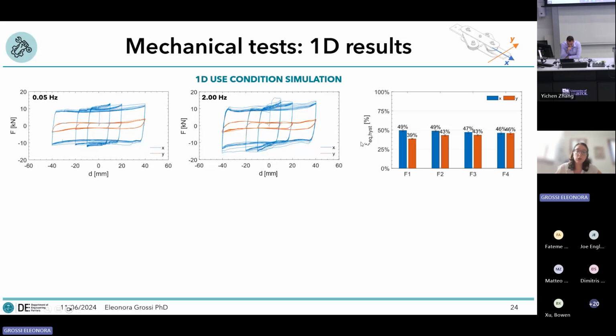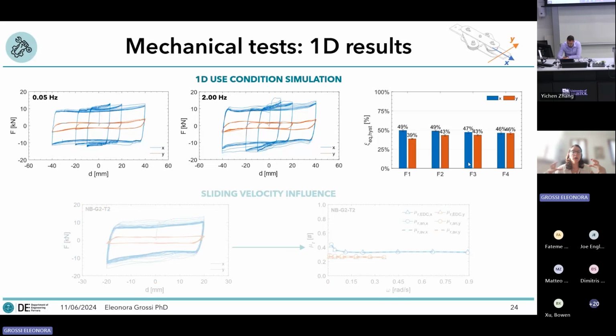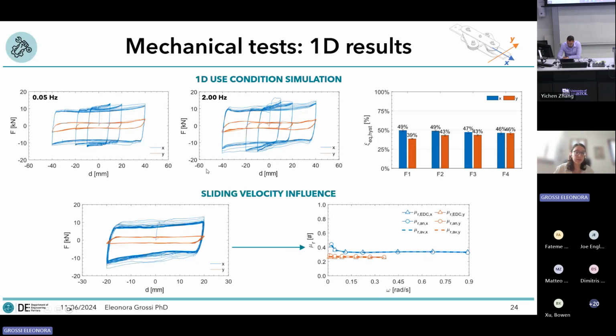This is also confirmed when computing the equivalent damping using Jacobsen formulation. You can see that the values along the longitudinal and transversal direction are quite the same and are almost unvaried. When focusing on the sliding velocity influence, you can see that the hysteresis cycles are slightly more rectangular. This is because of the type of signal that was applied, and also that there is quite a small influence as a function of the rotation velocity. You can see here that the friction coefficient that I evaluated is likely bigger at the smaller velocity. In here, you can see also that I computed the friction coefficient in 2 different ways.